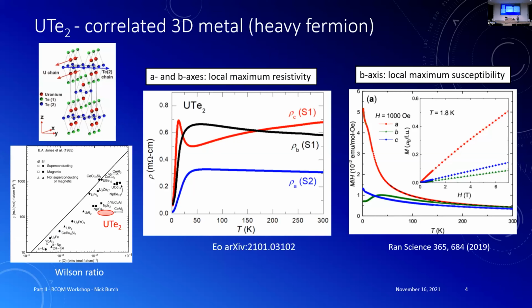Okay. So first thing, UTe2 is a correlated 3D metal. What I'm showing here on the screen, let's just start in the middle, is resistivity as a function of temperature. It's an orthorhombic system, so there are three high symmetry directions, a, b, c. There's a negative slope in the resistivity, a hump, which I'd say is typical of heavy fermion resistivity. The c axis has this interesting temperature dependence.